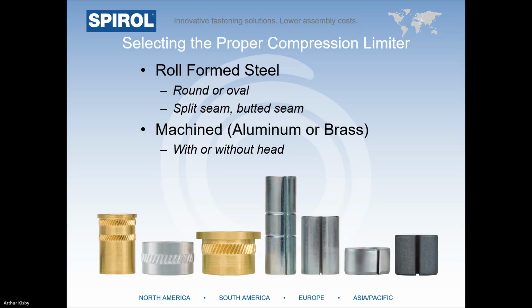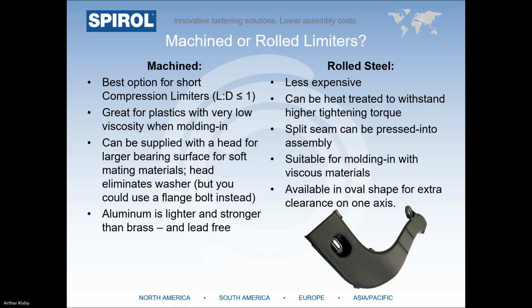A head can be added to increase the bearing surface against the mating component of the bolt. Unless there's a concern with galvanic corrosion, aluminum is generally preferred over brass because it is lightweight, lead-free, and stronger than brass. In terms of how to choose between machined or roll form limiters, the reality is that when it makes sense, rolled steel is definitely the most economical option.